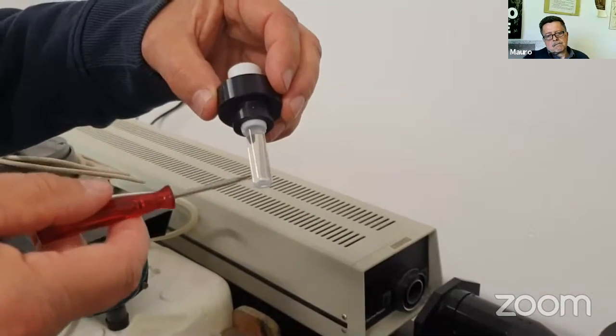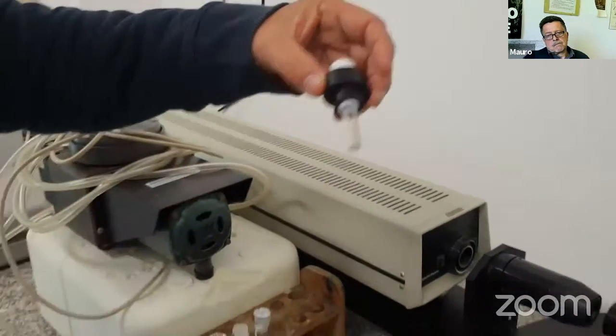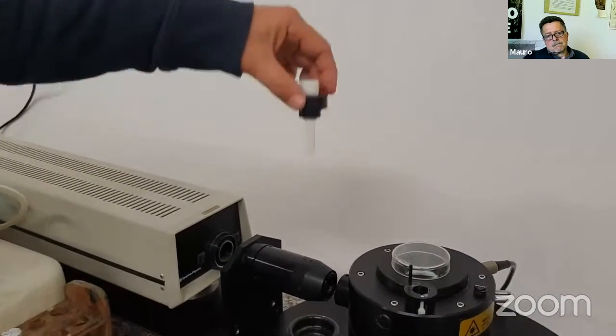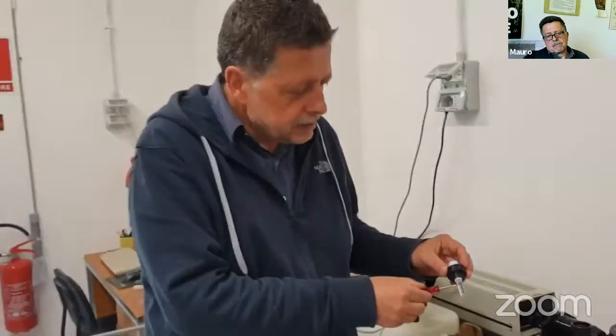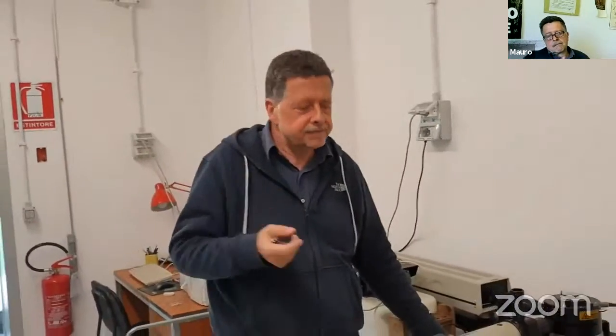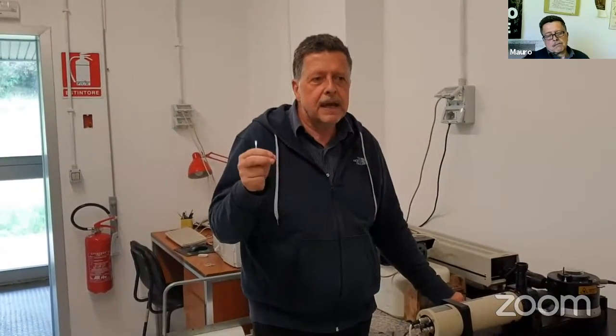The small particles in the suspension do not settle down because of Brownian motion. So when you shine light by a laser on this kind of sample, the particles diffuse light. Each particle in the suspension diffuses light, and the light diffused by the different particles interferes with each other. So there is a pattern of, say, light and dark that, however, changes because the particles are moving. So the interference will change from bright to dark according to the relative movement of the particles. And then by analyzing these intensity changes, you can go down to the velocity of the particles and finally to the particle dimension.